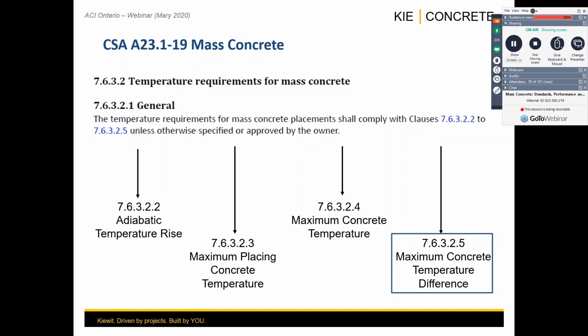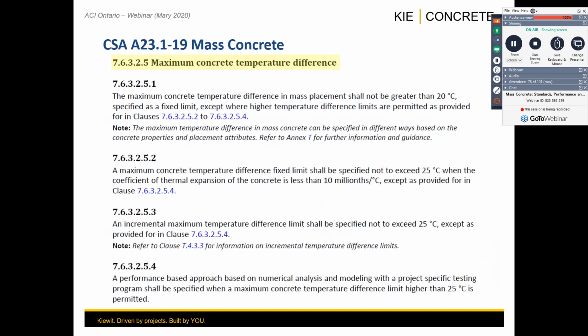So we have now different considerations that I'm going to be explaining here, and you're obviously going to be seeing that in the CSA standard. So the first one is 7.6.3.2.5.1. That one pretty much uses that 20 degrees Celsius fixed limit as the temperature differential, okay? So it pretty much establishes the same that we have been using to date. You say that you're going to have 20 degree maximum differentials, and that's your specification. That's all you want to do.